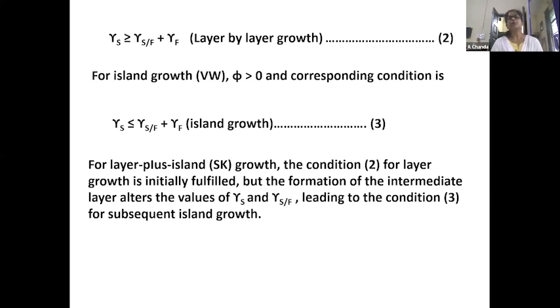And for island growth, that is Volmer-Weber mode growth, phi is greater than 0. The corresponding condition is gamma S is less than or equal to gamma S/F plus gamma F. Here island growth occurs. And for layer plus island growth, condition 2 is first satisfied, and then intermediate layers alter the value of gamma S and gamma S/F, leading to condition 3 for subsequent island growth. These are the mathematical discussions. Earlier we saw surface preparation, then adatom formation, then diffusion, then cluster formation. Those things are theoretical, and this is your mathematical part.